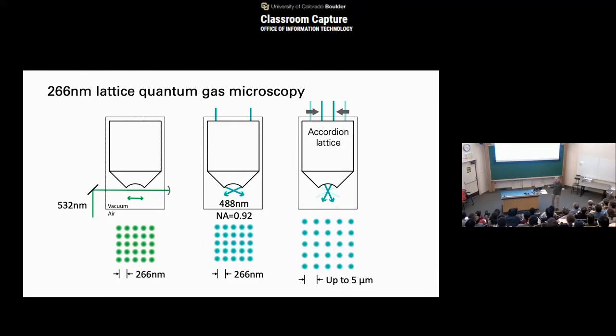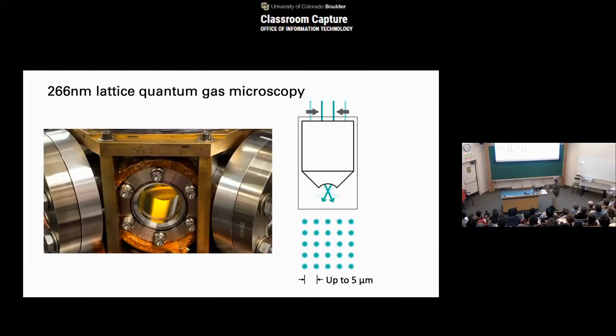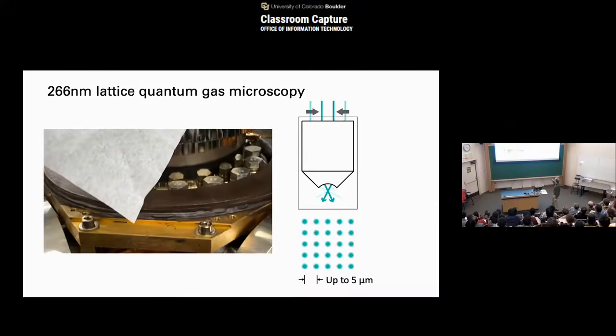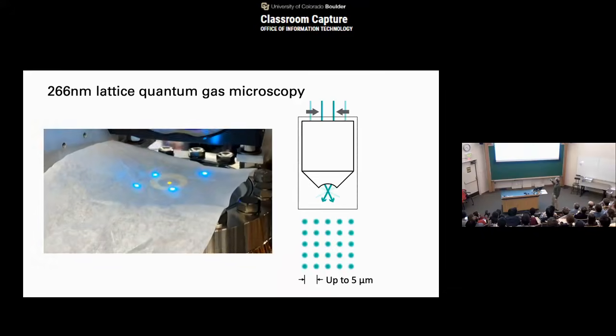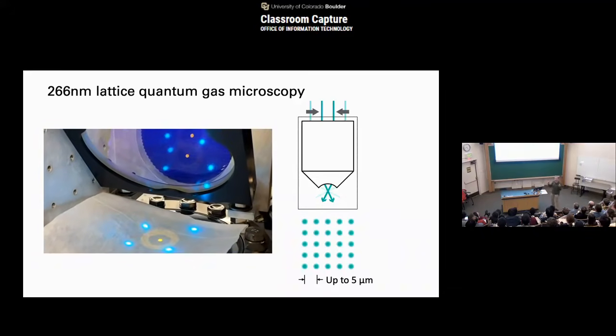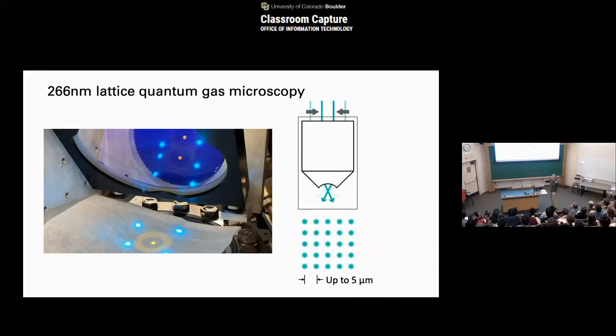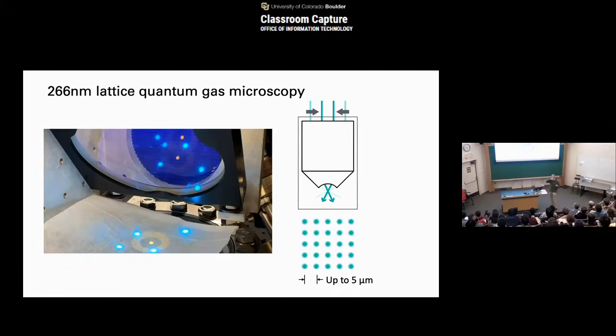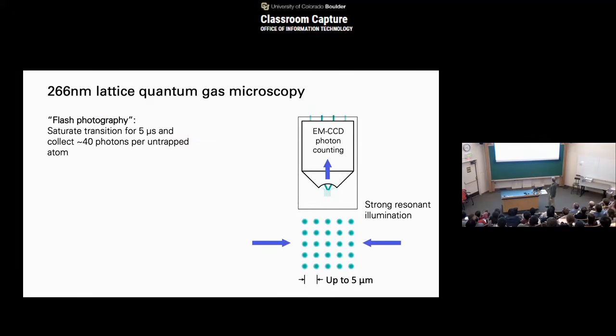And we designed a way that also makes that very doable in real life. Here you can see just a little movie: the objective is behind here, and in the Fourier plane you can see how these beams move in and out with galvo mirror-driven periscopes, and then we have a specially built optical setup that creates pairs of beams that move against each other and make this accordion lattice. And once we do that, of course, we have a large spacing between the atoms, 5 micron spacing. So now we can very comfortably and easily image the atoms within only a few microseconds.